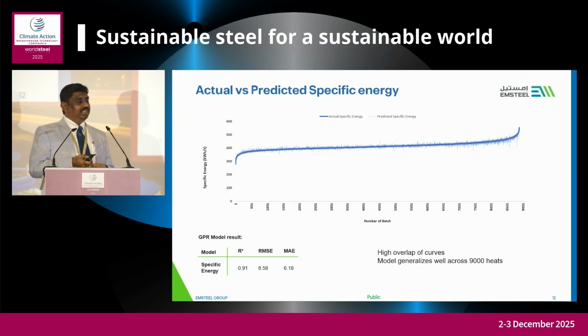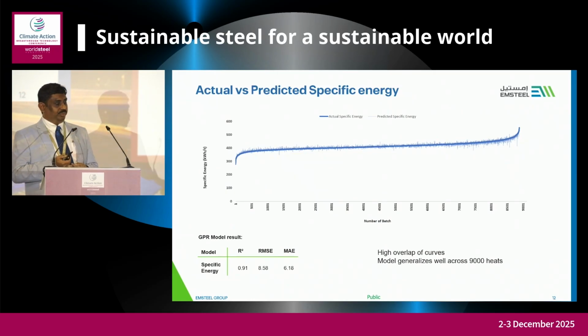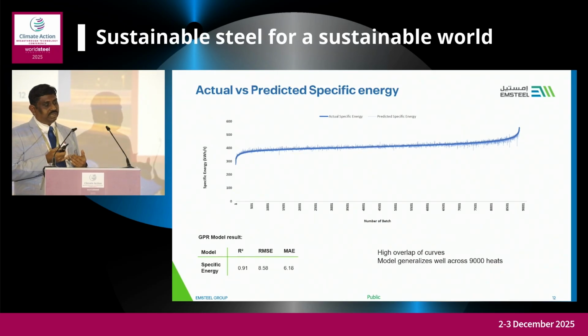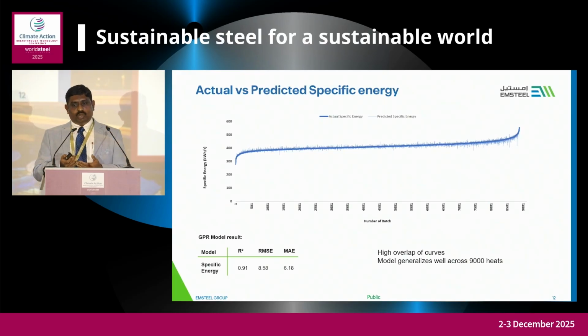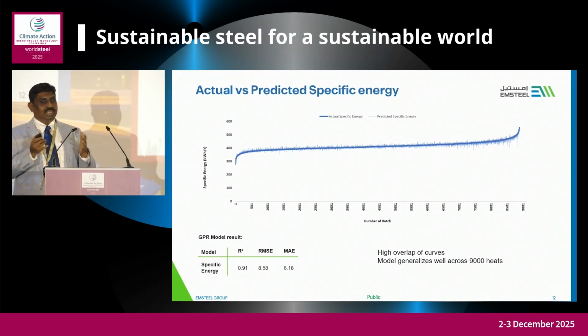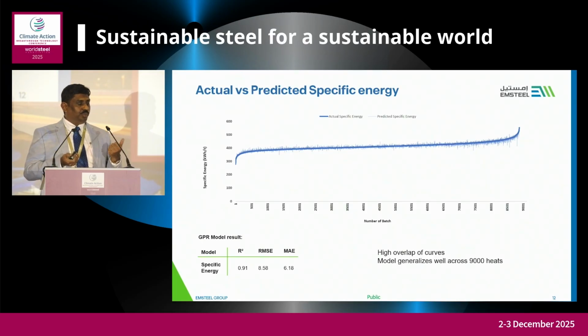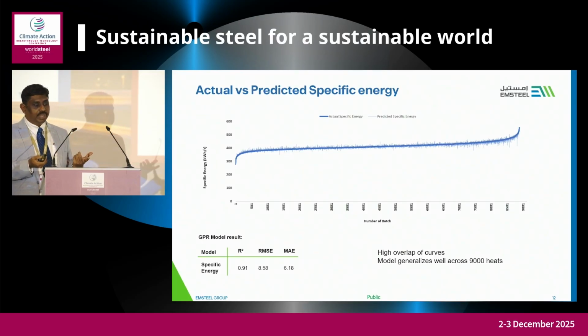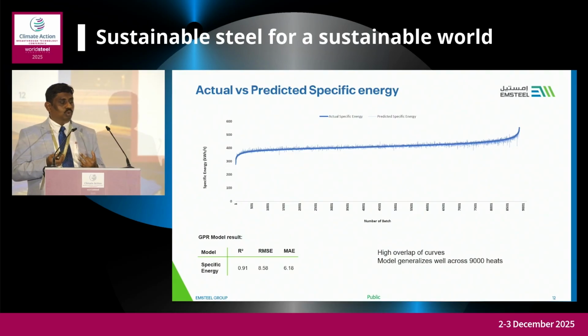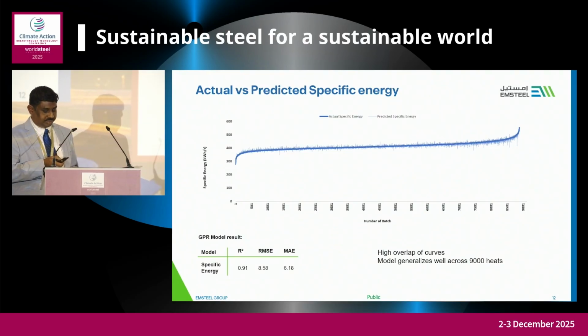Then if you see, this is the actual versus predicted specific energy. We have plotted the S-curve. What is the benefit of plotting the S-curve? We want to capture whether it follows the trend even at the minimum and maximum positions. This model has an R-square of 0.9, which is very high accuracy, and it follows the trends of the actual measurement.